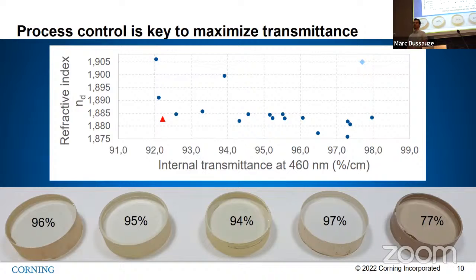before, which was a glass for ophthalmic application. So it was really for just lenses. And for this application, you don't care about the internal transmittance to be so high because the optical path is really thin. It's just going through the eyepiece. So this glass was made for lower density and high refractive index. So we were at 1.88 of refractive index, around 92-93% of internal transmittance at 460.